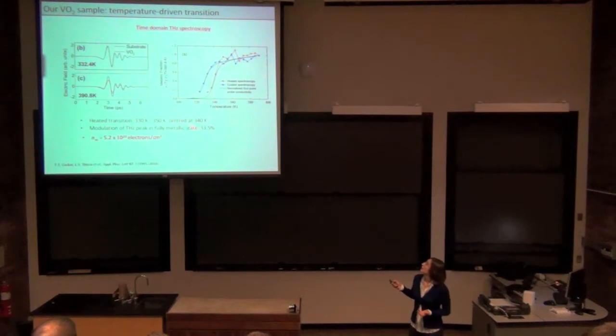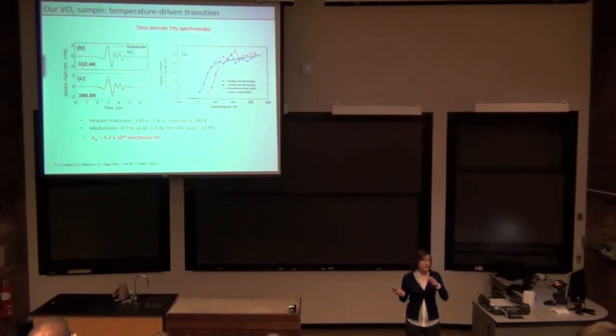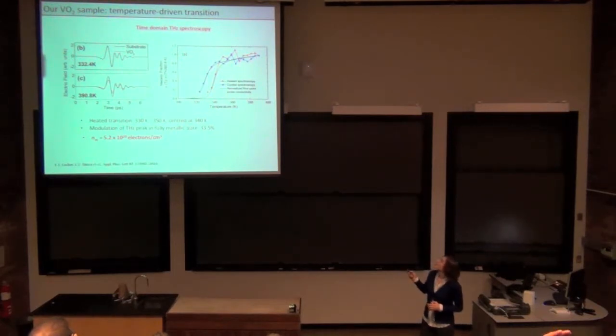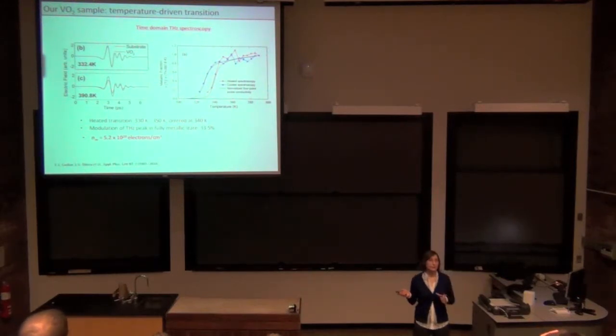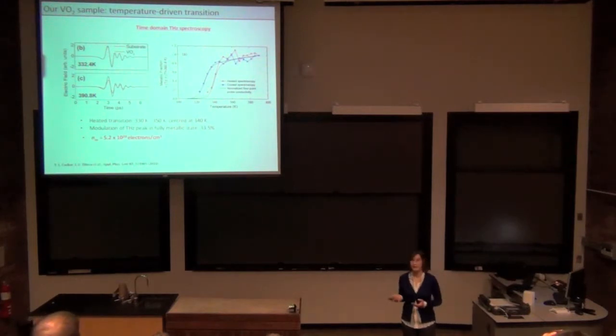If we take the spectra as we go through the transition, heat it up, and then cool it back down, and normalize the instantaneous carrier density to this number, we can actually get the fraction of the grains that have been switched. So here is our heated transition, cooled transition. The other thing you see is that it actually reproduces quite well your normal 4-point probe measurement, which was very reassuring to see.